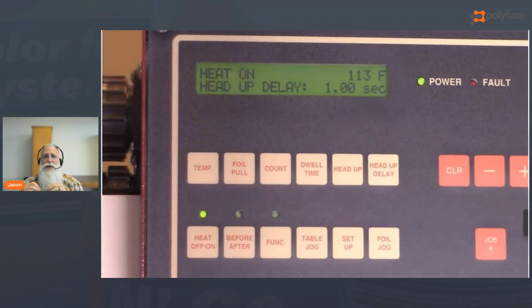For example, linear low density polyethylene is going to melt a lot quicker than, say, talc filled polypropylene. So when you get into polypropylene, it automatically has a longer dwell time than, say, polyethylene. High density polyethylene is going to perform different than low density, and ultra high molecular weight is also going to perform differently. So again, I work with 2 seconds and then adjust up or down as needed. And so with that, when I start at 2 seconds, if everything looks like it's properly fused, I'm going to do a crosshatch tape test.